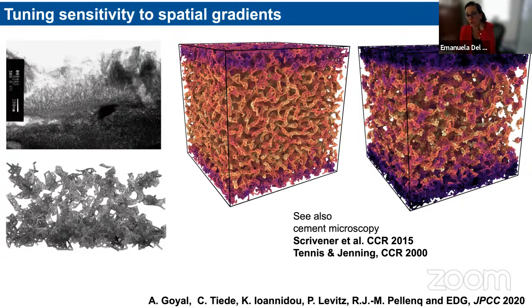In this type of simulation, it's interesting because you can gradually introduce different types of heterogeneities, a gradient in density, a gradient in the chemical potential, due to the fact that the material will start to form and dissolve from the surface, precipitating from the surface of the grains in the powder, because this is where it starts to dissolve. And so you can play with this type of feature in the simulations, and you can obtain different types of structures with different degrees of density.